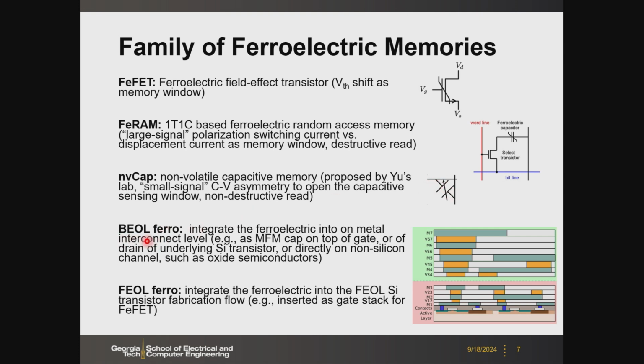In terms of where you can integrate the ferroelectric, there is the front-end-of-line integration, where you insert the ferroelectric into the gate stack, for example in the FE-FET with the silicon substrate. Or you can do the integration at the back end of the line, which means on top of the interconnects. You can put the FE cap on top of the interconnect, and you can also do the FE-FET using a non-silicon channel in the back end of the line. For example, typically people integrate it with an oxide semiconductor as a back-end-of-line oxide FE-FET.